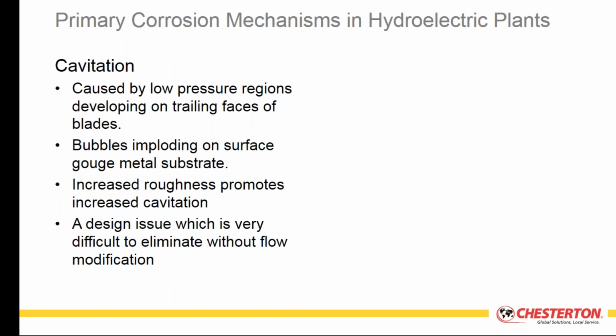Another form of corrosion, which is actually a mechanical method of attack, is called cavitation. Cavitation is quite common in hydroelectric facilities. We see this, it's typically caused by low pressure regions which develop in the trailing faces of the turbine runner blades. The air bubbles in the water implode on the surface under extremely high force.